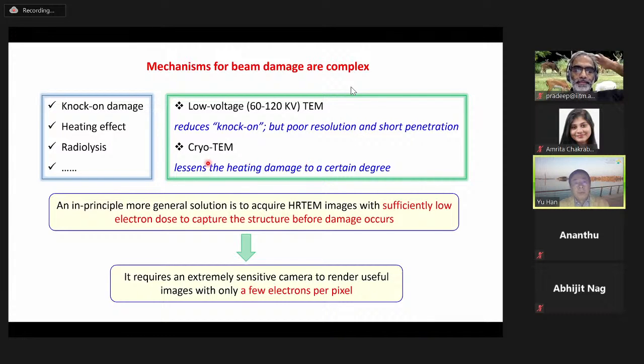And likewise, one can perform TEM at cryogenic temperatures, the so-called cryo-EM, right? You can lower the operating temperature, so you can minimize the heating effects. However, this doesn't help to reduce the damage caused by other mechanisms. So similarly, low temperature or cryo-EM is not generally applicable to all applications. So here we propose that regardless of the exact damage mechanism, the damage is caused by electrons interacting with the specimen, right? So if we can acquire images with sufficiently low electron dose to capture the structure before damage occurs, then this problem can be largely solved, right?